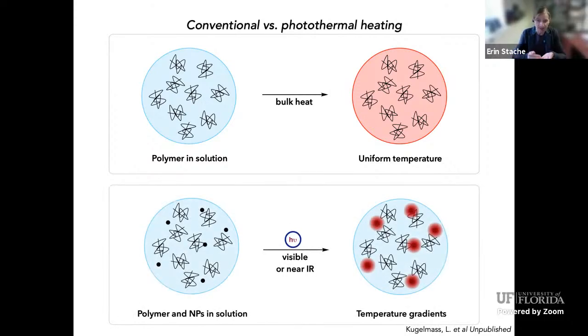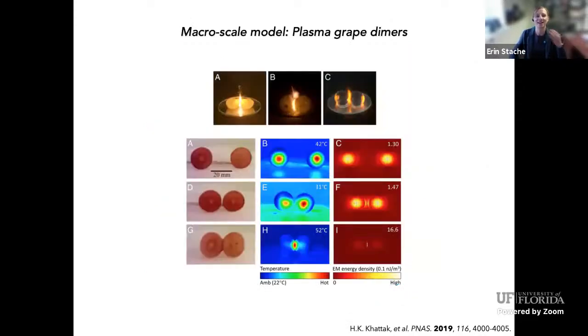You get a very uniform temperature across the entire form. Photothermal heating is very different. In this case, you're only getting heating at the surface of these nanoparticles, and it decays pretty quickly as you move away in nanometers. And so these are basically little nano heaters. And so you have all the temporal and spatial control of visible light, but your active stimulus here is actually heat, which is just a super cool concept.